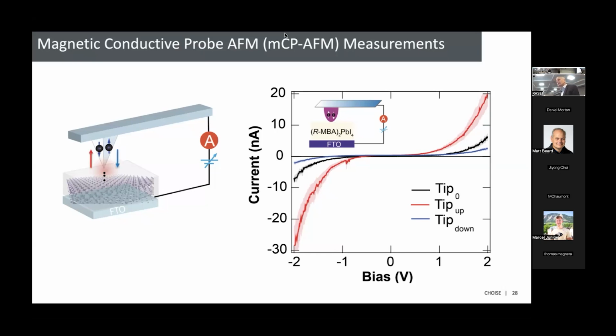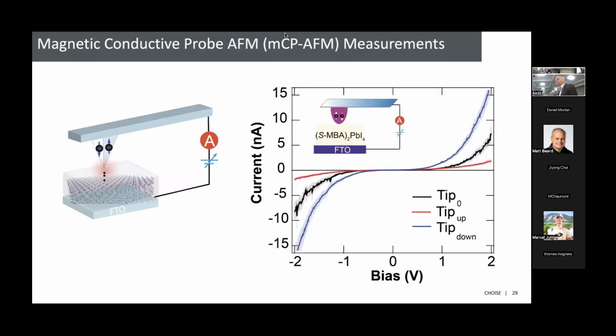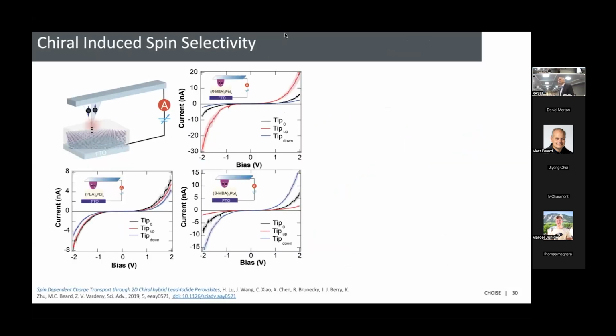Interesting. So what does that mean? That means, okay, if you magnetize the tip, you inject your spins up at the Fermi level and you block the other spins. And then when you change to the S version of the perovskite, you get the opposite behavior. Now, when the tip is magnetized down, you get good conductance, and if the tip is up, you get blocked. So that means now the other spin can get through the system. So now what that means, of course, is we have a way of preparing spin polarized electrons.